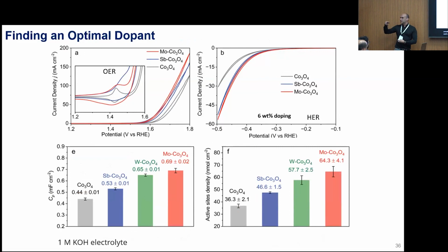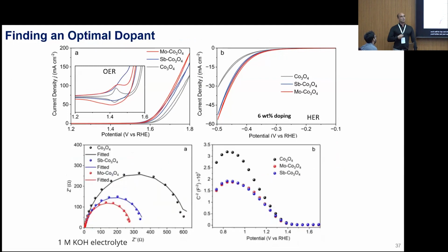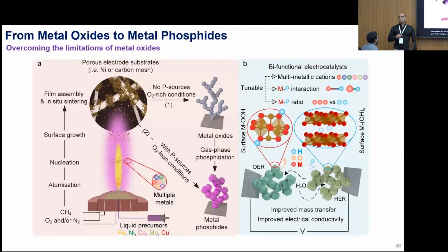But we are reaching the limitation. It's very hard to push it further, and in my opinion, it's still not good enough. So we switched gear and we said, okay, why don't we forget about these oxides and go to the phosphides? Because the phosphides can be much better conductors than oxides. Plus, you have multiple opportunities to change the surface activity and properties inside, right?